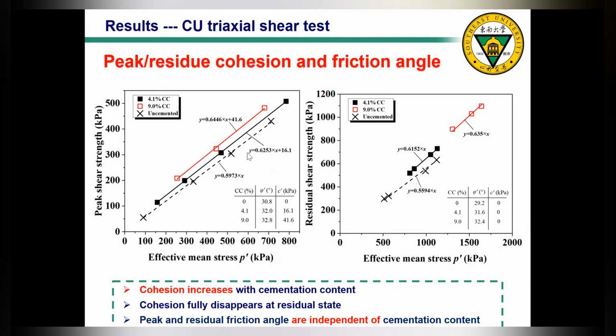So obviously, with biocementation treatment, the effective peak cohesion increases from 0 for the uncemented case to 41.6 for the high cementation level case. However, if we look at the effective friction angle, actually it does not change too much. So it means that the peak friction angle is sort of independent of cementation content. Then for the residual state, firstly, we find that the cohesion is fully mobilized. So there's no cohesion at this state. It means that all effective bonding has been broken at the residual state. And secondly, if we look at the effective residual friction angle, again, it does not change too much with the cementation content.